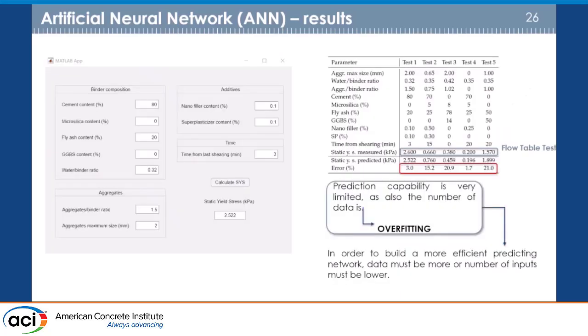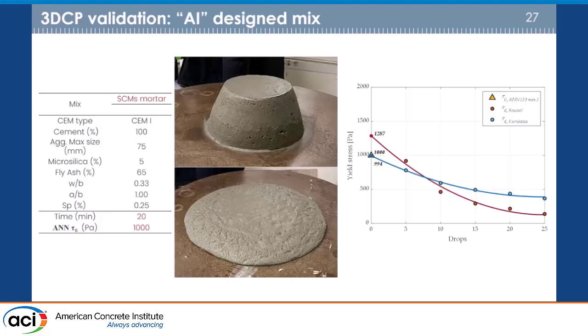But what was quite interesting is that in the end, we tried to design 5 mixes completely from AI, basically, and we obtained reasonably good predictions. Just in one or two cases the error was fairly high. There is also the problem that with such a low amount of data, you can risk in some cases overfitting of the network, because it has learned to be too good in making this performance. But in the end, among these 5 mixes, we selected one that was able to fulfill the predictions that we have both from the literature, and the AI worked fairly well in giving us mixes which behaved well,